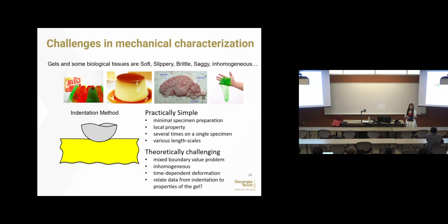But comparatively, indentation is very simple. You just have the sample there and compress on it. But the difficulty of using indentation is mostly from the theoretical aspect. Different from tensile testing, this is inhomogeneous deformation. And when you consider this coupled deformation and diffusion, it's even more complex. Within this contact area, you have a displacement boundary and an impermeable boundary, and outside is permeable. You can use finite element simulation to calculate this problem, and there is no problem with that. But the goal here is to generate an analytical or semi-analytical solution so that people without a mechanics background who do not know how to run simulations can extract the material properties by themselves.